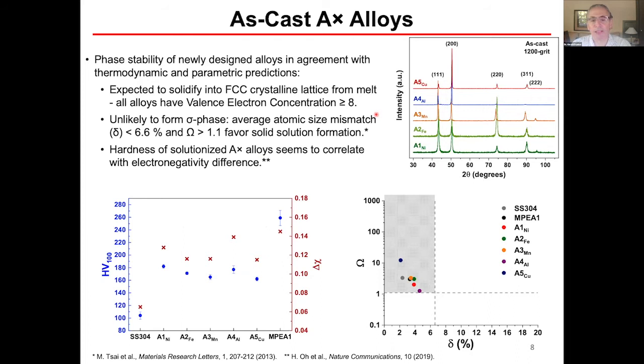Okay, so like those other alloys, we arc melted them and cast up buttons, and indeed there are solid solution FCC structures. That's predicted based on this valence electron concentration being greater than 8 and the lack of phase formation related to the atomic size mismatch and this omega factor, which from this work by Tsai is in a range where we would expect solid solution formation.